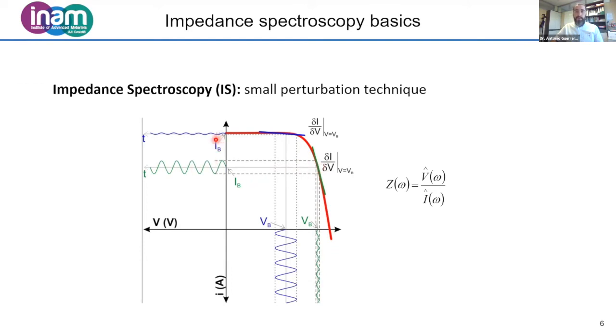So typically what we do is that we place ourselves in several parts of the JV curve, and we modify the AC voltage over several orders of magnitude in frequency. The impedance will be a function of the perturbation we are introducing, and can be calculated by dividing the voltage by the current.